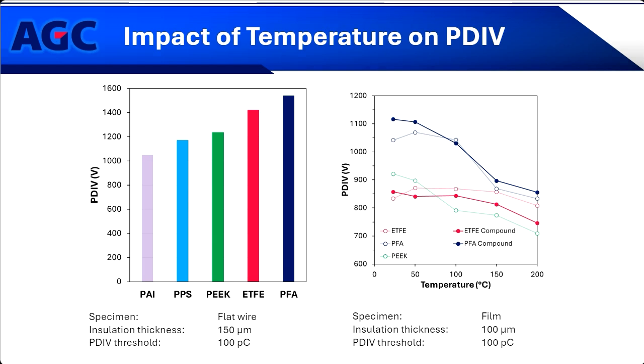So I also want to talk about the impact of temperature on PDIV. So I show here on the right the PDIV change as the temperature increases, starting at room temperature and then increasing all the way up to 200 degrees Celsius. These materials were thin films of approximately 100 microns thickness.